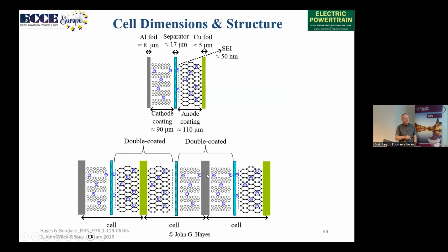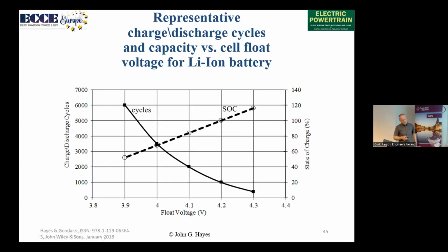But what we're going to do is double coat each of these foils. So these are very thin foils. For my numbers here, the aluminum foil is about 8 microns thick. The copper foil might be about 5 microns thick. The separator is about 17 microns thick. The cathode coating, in this case, I'm showing about 90 microns. The anode coating is about 110 microns, very, very thin layers. So we're looking across this at just over 0.2 of a millimeter as the thickness of each cell. And I say we're double coating the foils. So that was our structure.